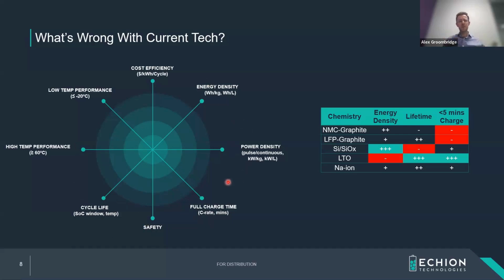If we look at standard lithium-ion battery technology that exists today, I've broadly categorized, tried to make it pretty simple, with NMC graphite, NMC being the cathode, LFP graphite, silicon-based anode chemistry, LTO-based anode chemistry, and sodium ion. And we can see, to try and hit these metrics of energy density, lifetime, and chargeability, NMC graphite, good at energy, silicon even better. But when it comes to the lifetime requirements of such high utilization applications, they're simply not a good fit. They fall away too quickly.